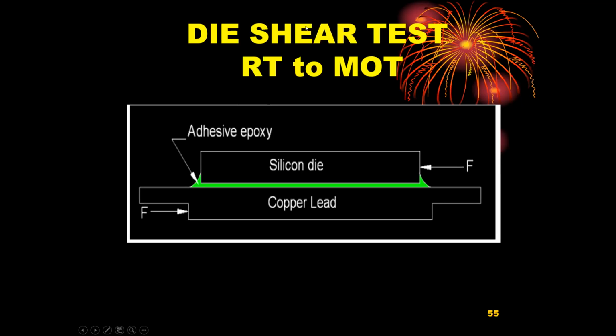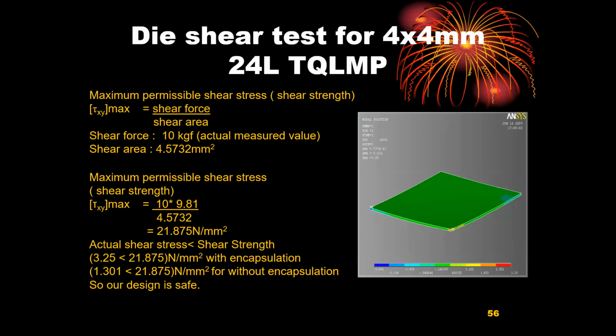Coming to the experimental die shear test, we also had to worry about what would happen to the copper lead frame and the silicon die attached, at the temperature up to the maximum operating temperature. So a shear strength of 20 megapascals or 30 megapascals might decrease at the maximum operating temperature of, say, about 50 or 60 degrees Celsius to 5 or 10 megapascals, which may make it very easy for the silicon die to shift and then dislodge the wire bonding, or any of the constructional integrities.